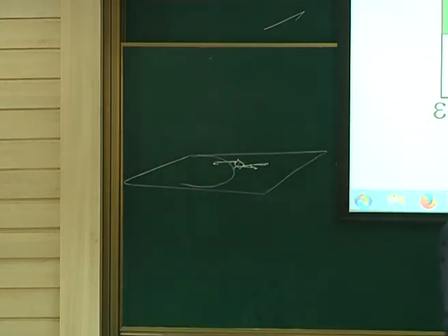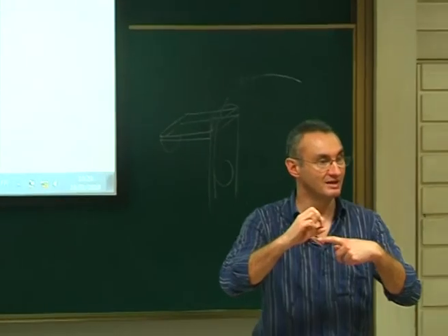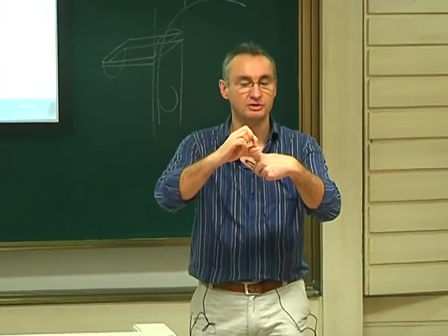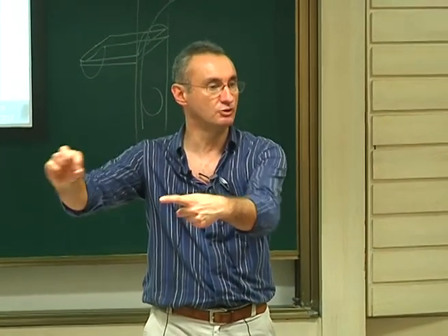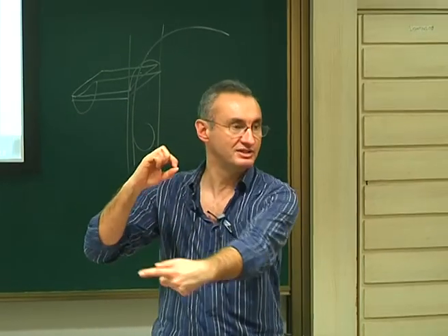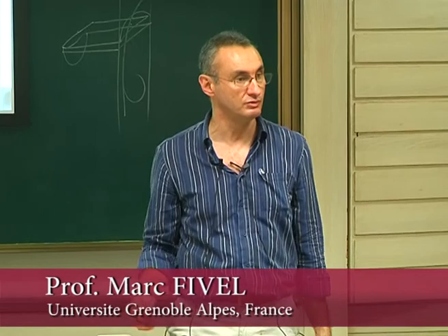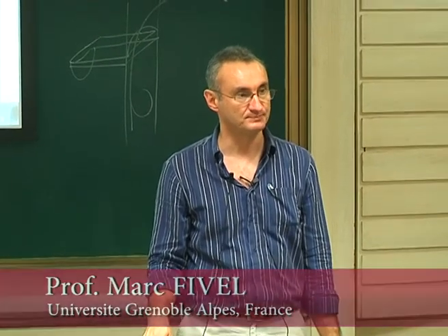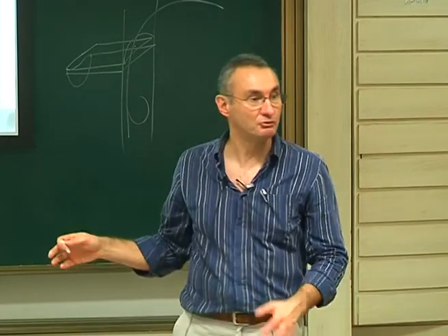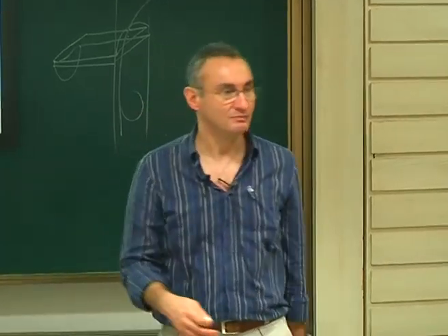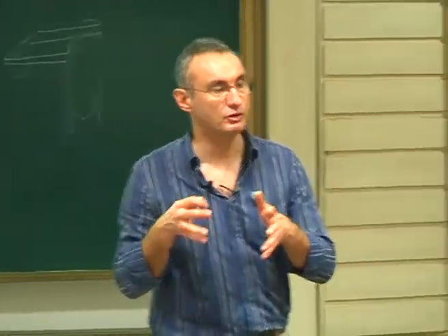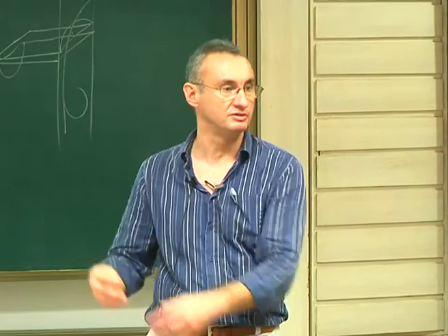But there is a study from Bacon, I think, that they did it. Actually, this sweeping mechanism depends very much on the velocity of your dislocations. If your dislocation goes slowly, you can sweep your prismatic loop. If it goes fast, you can move and detach. All possible mechanisms occur, and you will see with NuMoDiS it works. We found that also. So I don't explain this, but the idea is that it will create a gradient, and the gradient will move the dislocation. That's the idea.